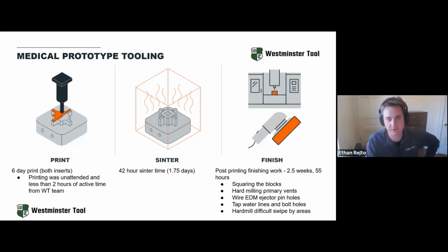What were the steps involved to produce this with Mantle? There were 6 days of printing. That's to produce both of the inserts, which we'll look at on the next slide here. Of course, all that printing was done unattended, so a total of less than 2 hours of active time from the Westminster Tool team. They sintered the inserts, so again, unattended, but about a day and a half in the furnace. And then they did about 2.5 weeks of finishing here, or 55 hours of finishing,